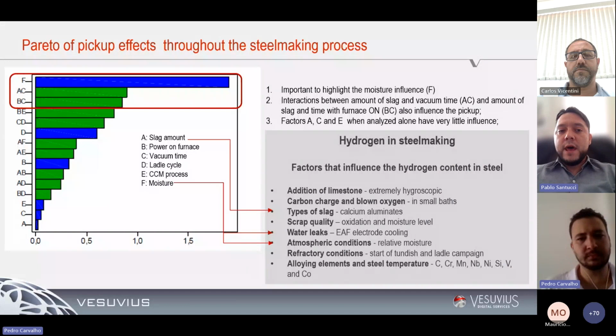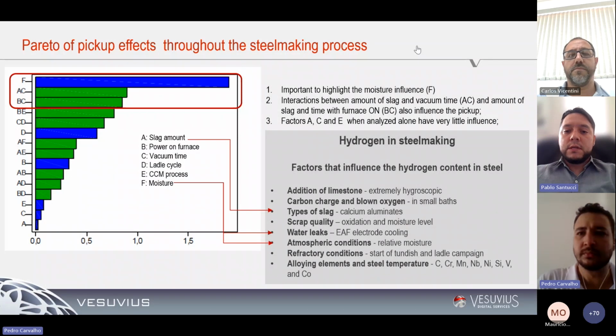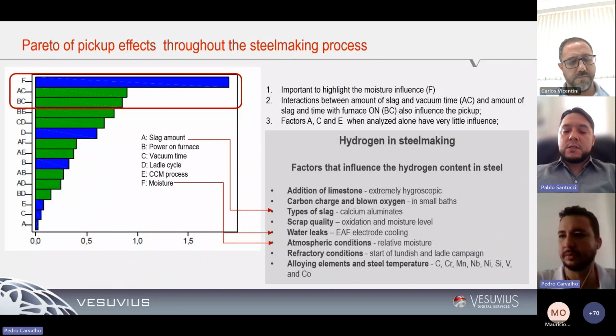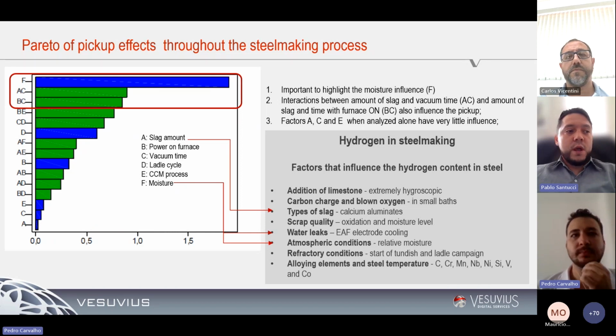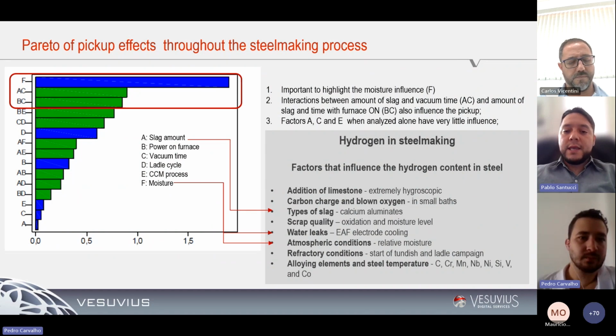Yes. Based on that, this is a Pareto analysis that has been made over a long time that shows the main top offenders, or the main causes of hydrogen presence in the steelmaking process. For instance, we can have a hydrogen source due to atmospheric conditions. For example, scrap can get wet in the rainy seasons, or the humidity of the atmosphere is too high. That can contribute to having high hydrogen content inside of the steel.